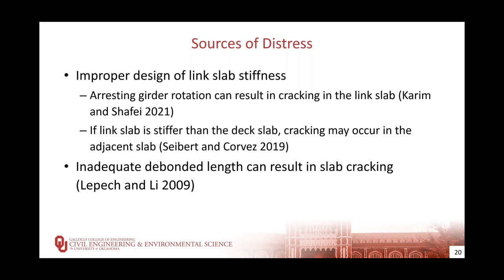A significant concern is the degree of cracking in the Link Slab and bridge deck over the piers, which can be affected by an improper design of the Link Slab stiffness. If the stiffness of the Link Slab is such that the girders cannot rotate properly, substantial cracking may occur in the Link Slab. If the Link Slab is stiffer than the surrounding deck slab, this cracking may not occur in the Link Slab, but may occur in the adjacent decks.